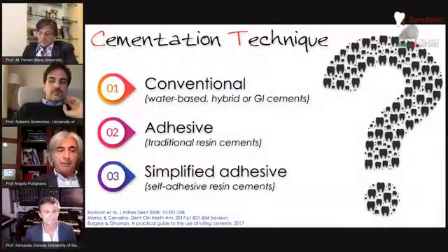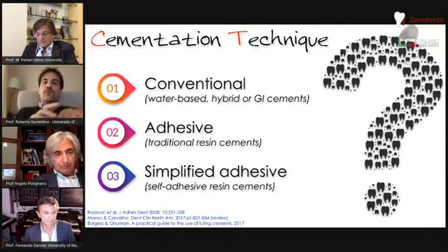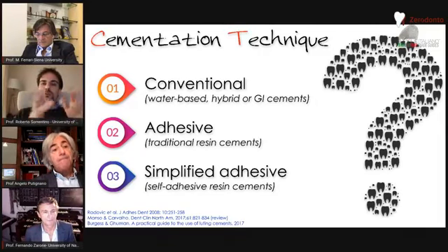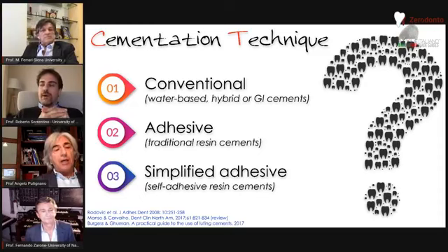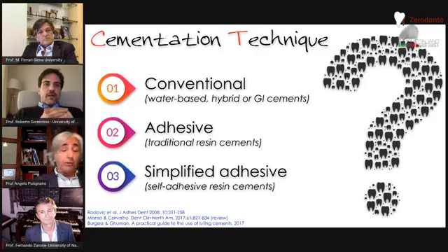That's paramount. I prefer to sandblast the enamel before etching, if I have enamel. Prof, do you use the AquaCare solution for sandblasting or traditional powders? I use AquaCare. AquaCare, perfect. Or Rondoflex by KaVo is the same, so underwater. In this way, you are more precise, you don't spread, but even if I am under rubber dam, no problem. But after that, for the environment, it's better to use the water.